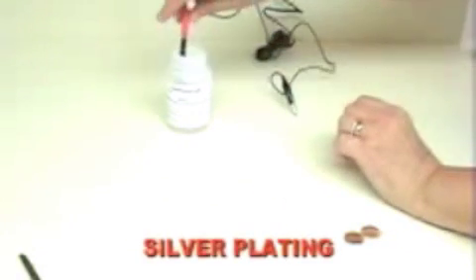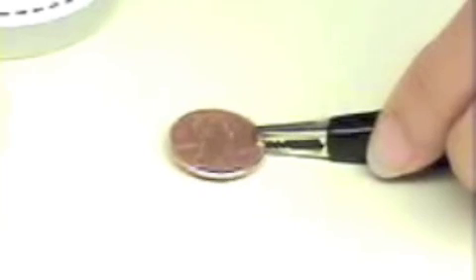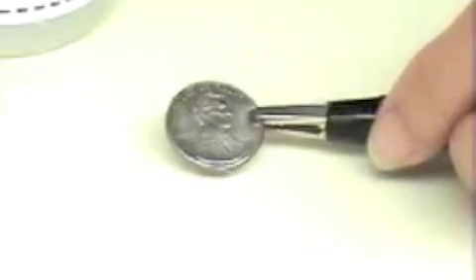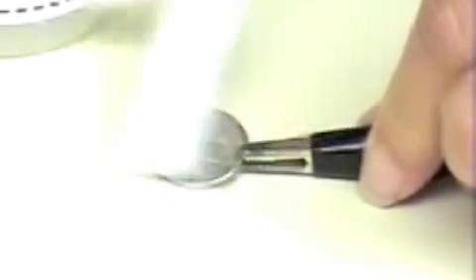Silver plating uses a 1.7 volt adapter. It plates very quickly as you can see here. Initially you will see a lot of black smut. This is normal. Keep plating, moving the wand more rapidly than with the other solutions and with a little firmer pressure. The black smut will usually disappear.